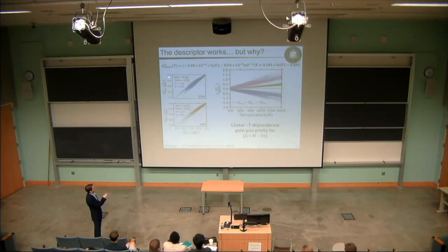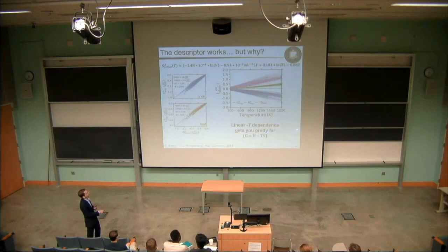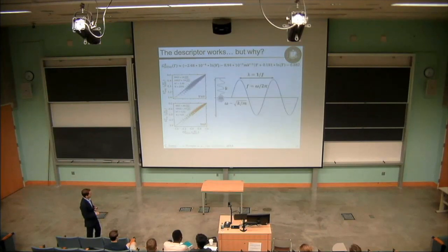So again, we have this relatively tangible descriptor, so we can start to parse out what is the meaning of the relative terms. So the incorporation of temperature is not so hard to explain. We know that intrinsically the Gibbs energy is the enthalpy minus the temperature times the entropy. So we inherently already have this negative temperature dependence. We can also look at these slightly more involved terms. So this is the atomic density, so how packed are the atoms together, and this is the reduced mass.